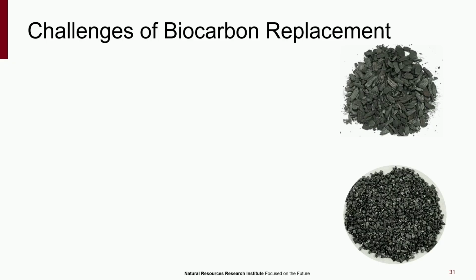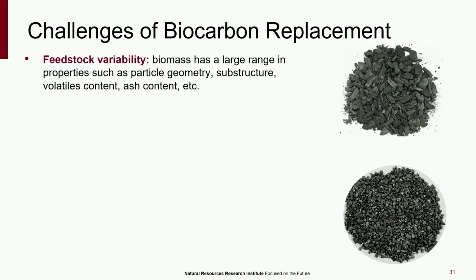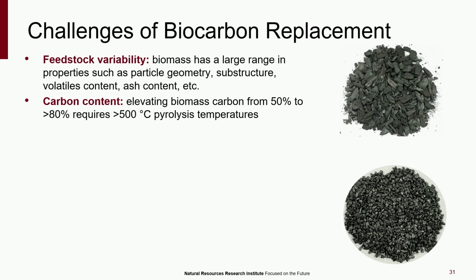So as you can imagine, there are a lot of challenges that we encountered when looking at a biocarbon replacement. First off, feedstock variability. Any biomass stream is going to create a different type of biochar, and so we had to play around with lots of different feedstocks to get the geometry and substructure and volatiles content, ash content that we wanted. We also knew that we needed a high fixed carbon, so we needed to go from about 50% fixed carbon to greater than 80, which requires a high pyrolysis temperature.